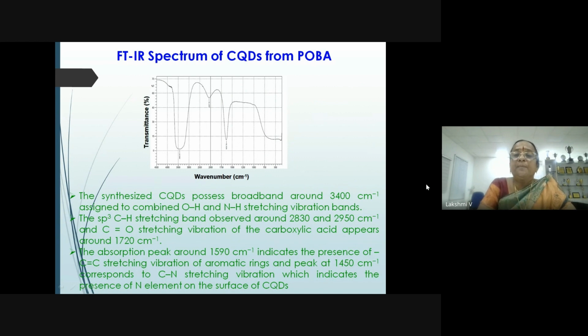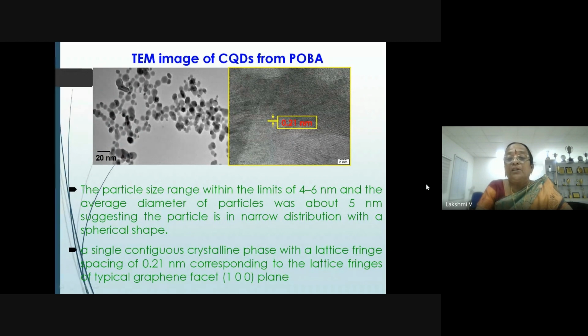FTIR spectrum of CQDs from POBA. The synthesized CQDs possess a broad band around 3,400 per centimeter assigned to combined OH and NH stretching, which can happen in the layers. The sp3 CH stretching band is observed around 2830 and 2950 per centimeter, and C double bond O stretching vibration of the carboxylic acid appears around 1720 per centimeter. The absorption peak around 1590 per centimeter indicates the presence of C double bond C stretching vibration of aromatic rings, and the peak at 1450 per centimeter corresponds to CN stretching vibration, which indicates the presence of nitrogen element on the surface of CQDs. This is the TEM image of CQDs from POBA.